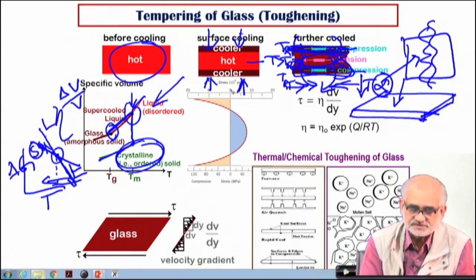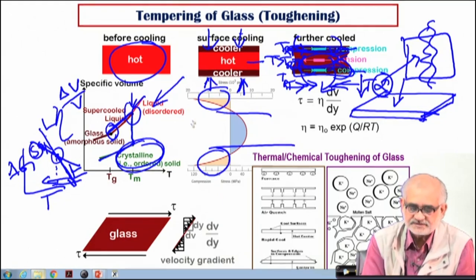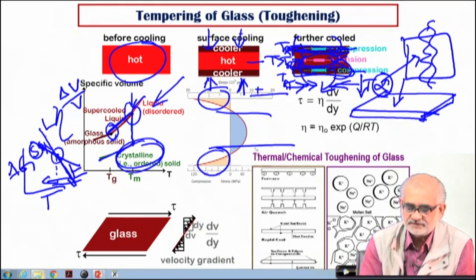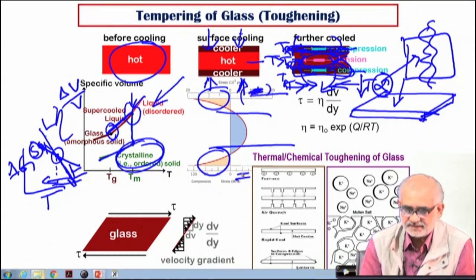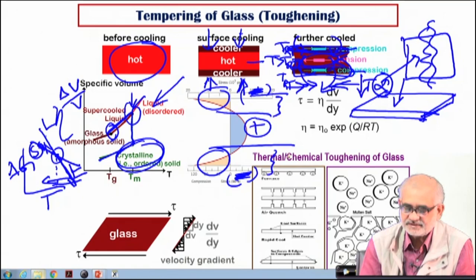This part will be under compression — the surface will experience compressive force and will be seeing the negative forces, while the core will actually experience tensile stresses. This is inconsequential; what is important is that up to a certain thickness you are experiencing residual compressive stresses. Now when a projectile hits the surface of the glass, it first has to overcome these residual compressive stresses, and only then can a crack propagate. As a result the glass now acts tougher. This is how you can strengthen silicate glasses.